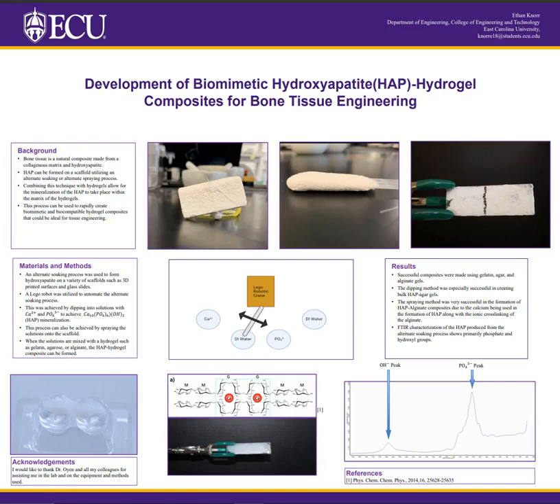For the results, I was able to successfully create hydroxyapatite gel composites from gelatin, agar, and alginate hydrogels. The alternate soaking process was very successful in creating good, strong, biomimetic hydroxyapatite agar composites. The alternate spraying process was very successful in creating hydroxyapatite alginate gels, especially because the calcium could be isolated and used as not only a part of the mineralization of hydroxyapatite, but also in the cross-linking of the alginate gels.